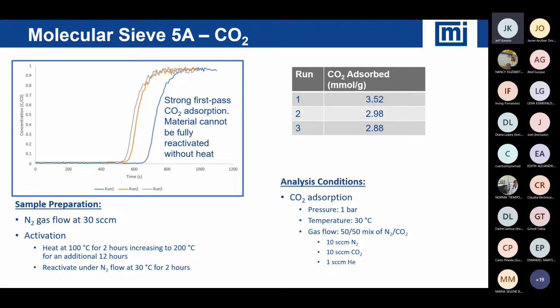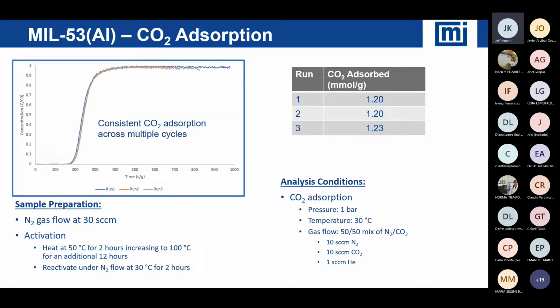We can change material, right? So you look at zeolite 5A, and you get quite a bit more adsorption, but the capacity changes rapidly. So the first cycle has the highest quantity adsorbed. Second and third cycle see some degradation, so you're not getting quite the same capacity you had. Metal organic frameworks, very good performance, very consistent. The difference compared to the zeolites, capacity is lower. Okay, very consistent, so very robust, but overall lower capacity.